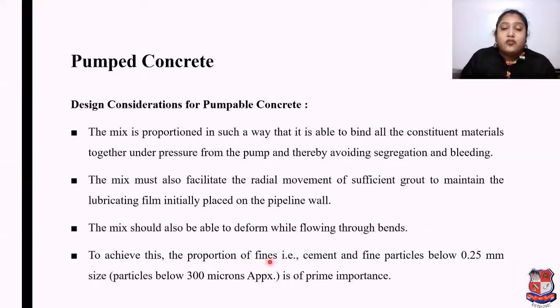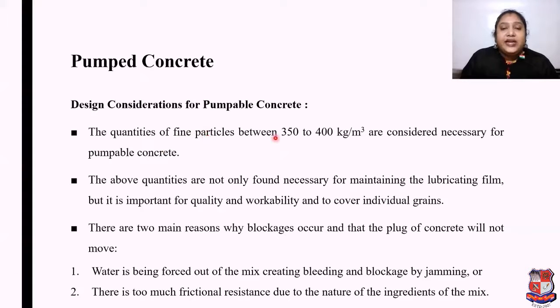To achieve this, the proportion of fines like cement and fine particles below 0.25 mm size, means we can say particles below 300 micron approximate, is of prime importance in pump concrete. The quantities of fine particles between 350 to 400 kg per meter cube are considered necessary for pumpable concrete. The above quantities are not only found necessary for maintaining the lubricating film, but also important for quality and workability and to cover individual grain in pump concrete. There are two main reasons why blockages occur and the plug of concrete will not move. These two reasons are, water is being forced out of the mix creating bleeding and blockage by jamming, or there is too much frictional resistance due to the nature of the ingredients of the mix in concrete.